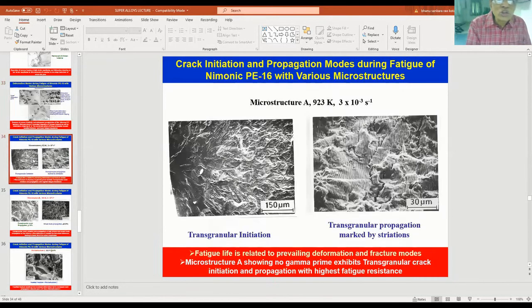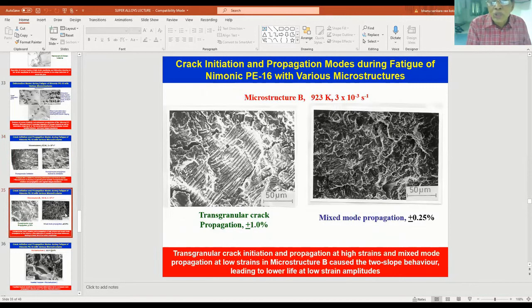You see, in the solution annealed condition, the fatigue crack gets initiated from the surface and propagates in a transgranular manner in the form of striations. This type of fracture is an indication of better fatigue resistance in the material in the solution annealed condition. You see in microstructure B, at high strain amplitude, transgranular crack propagation. At low strain amplitudes, you have mixed mode propagation, transgranular plus intergranular; striations are missing at certain places and intergranular cracks are there. So since you have the mixed mode fracture, fatigue life has decreased drastically at low strain amplitudes.